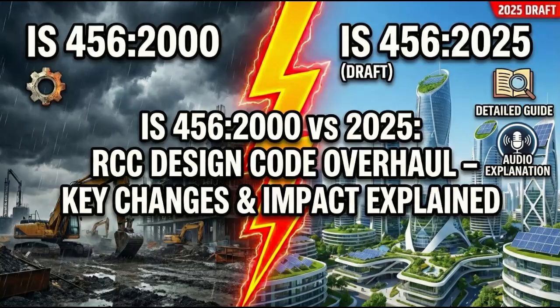Exactly. Based on 5 qualitative exposure conditions, mild to extreme, the code specified a fixed nominal cover, minimum cement content, and maximum water cement ratio. If you hit those 3 numbers, you are compliant. End of story. That seems fine for mild or moderate exposure, but what happens in aggressive environments? Well, in highly aggressive environments, particularly coastal cities like Mumbai, Chennai, or Kochi, that simple prescriptive cover often proved insufficient. So the building started to fail. Within 20 to 30 years, structures would exhibit severe corrosion due to chloride ingress because the prescriptive rule didn't account for the actual mechanism of degradation or the specific concrete mix being used.